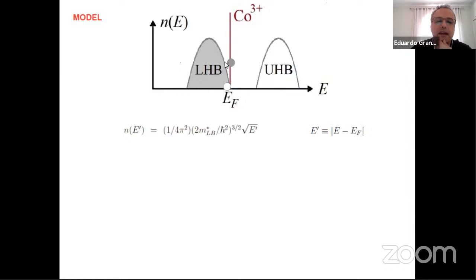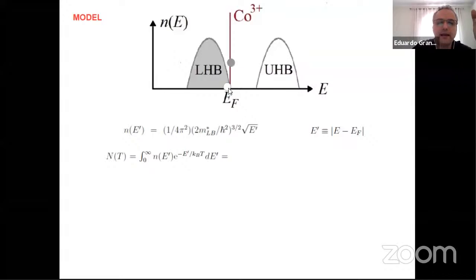So we have this density of states, which, for those who already went through the solid state physics course, you know is proportional to the square root of the energy, the difference of energy with respect to the Fermi energy. So that's the behavior of the density of states of this band. From that, we know the number of holes that we may have in the valence band due to a thermal excitation of electrons from the valence band to the impurity level. Because if you have this thermal activation from the valence band to the impurity level, that leaves holes in the valence band, which are thermally activated. So we are not at zero temperature, but at a finite temperature, we have these holes.